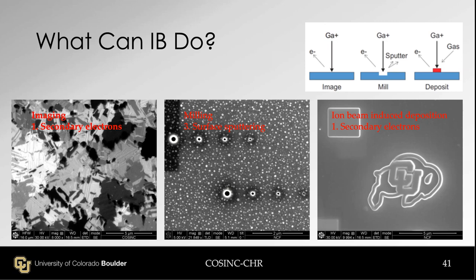And the right one, ion beam induced deposition. We can locally flow a small amount of gas, and those gas molecules can attach to the surface. Upon gallium ions hitting the surface, secondary electrons are generated. The energy of the secondary electrons can modify the property of the surface-adsorbed gas molecules. Then you can deposit some material, for the CU Buff logo. I believe this is platinum deposition. So three things we can do. With an electron beam, you can do imaging, and you can do electron beam induced deposition as well, but not milling.